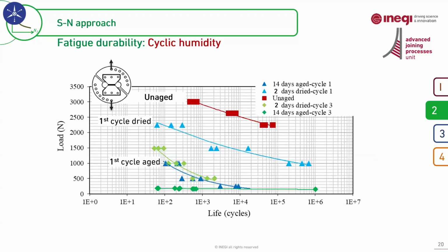I talked about cyclic humidity in the introduction, and we have investigated this phenomenon in detail in a PhD project in our group, with several important findings. One key observation is that the moisture ingress rate changes from cycle to cycle and stabilizes after a few cycles. We found that the rate of water uptake, the diffusion coefficient, is much higher under cyclic aging than constant aging. It means that if the environmental condition is cyclic, the joint will experience a higher rate of degradation in properties than when it's subjected to a constant humidity level.